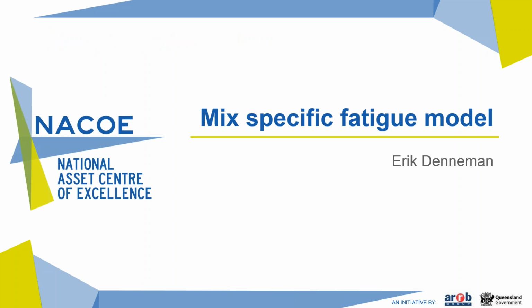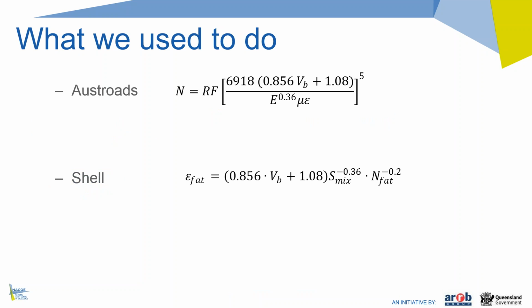Okay, so again, this is about developing mix-specific fatigue models. So instead of using the general model that is currently in the Austroads method, we'll be developing fatigue prediction models that are mix-specific. So this slide shows the current Austroads equation that you will be familiar with, which basically says that the fatigue performance of a mix in the field, or the number of cycles to failure, is a function of the volume of binder, the modulus, to take into account any changes in temperature and loading speed, and the strain level at the bottom of the asphalt layer.